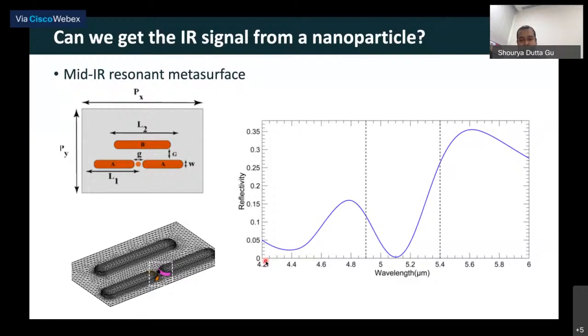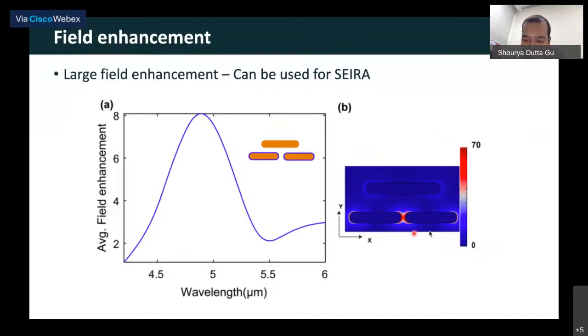So now, if you notice, we have multiple features again. So we have two peaks and one dip. So the resonance of the structure is near this peak and near this peak, right? Now, as we know, if we have high fields, we can also use those high fields for capturing objects. So that is shown here. So if you notice, between these two bars, we have a very high field. And if you actually plot it, it is maximum near that resonance that I was talking about, right? And the force that we apply on the object is proportional to the gradient of the field or gradient of the intensity. So the objects will get trapped in this particular gap here.